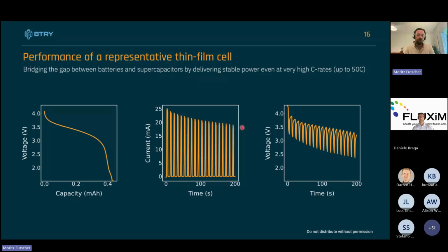If you now wanted to draw these currents of above 20 milliamps with something like a coin cell, you would probably need capacities in the order of 20 to 100 milliamp hours, because they can really only deliver the energy in a very slow manner. And this is really where batteries usually fail. That's why in IoT devices you often combine a battery with a capacitor. This technology can replace it and still electrochemically be a battery, store the energy for a very long time, but if needed, deliver very high current peaks.